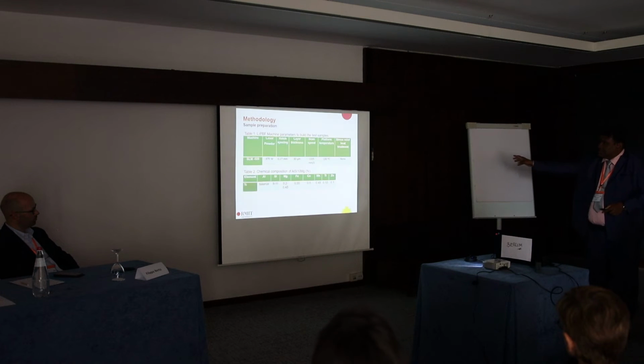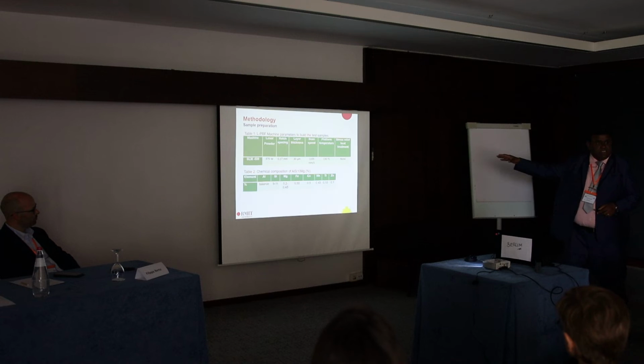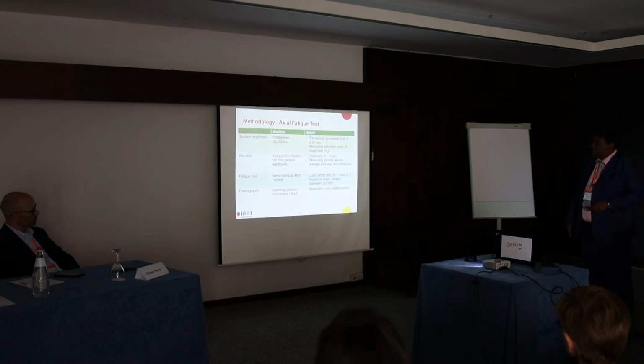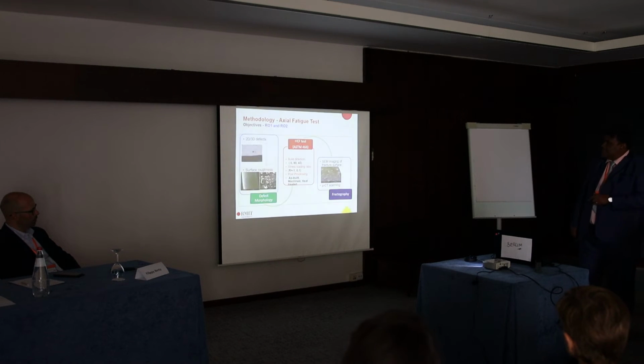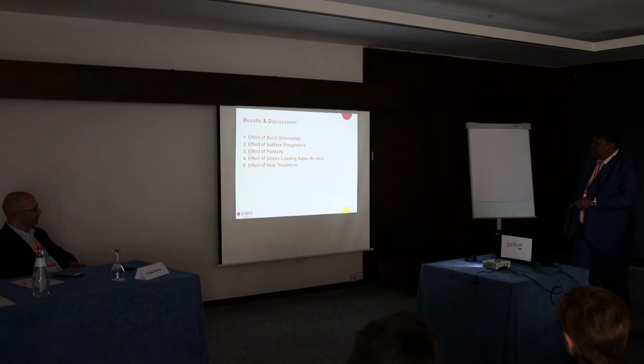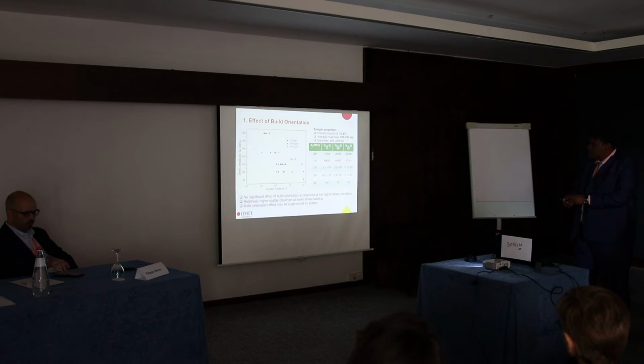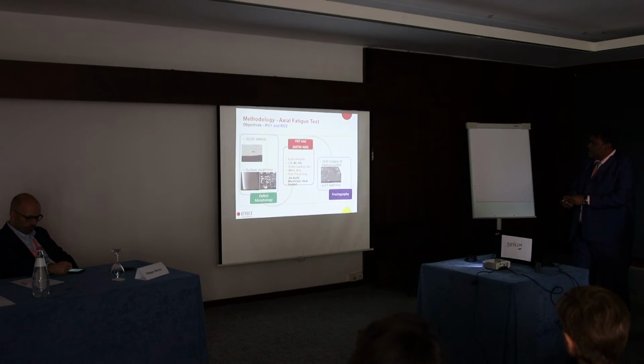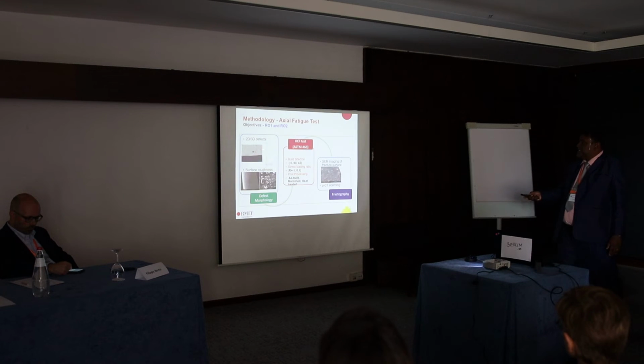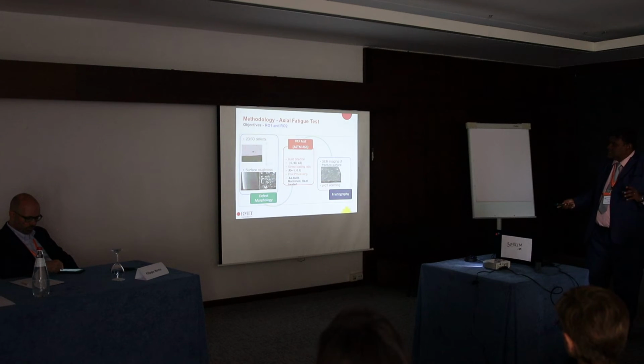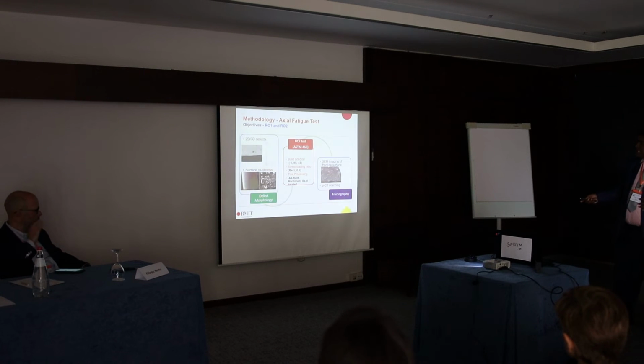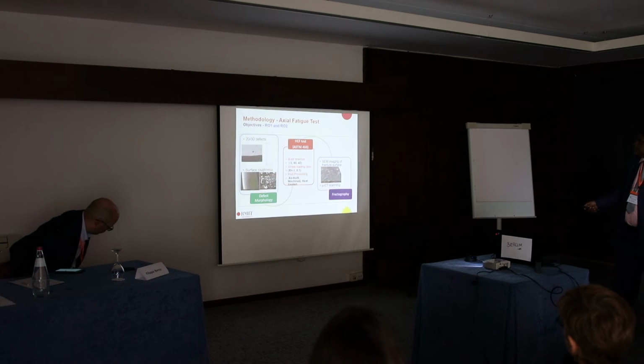This is the details of the presentation, powder composition, machining parameters. So if you're interested, I can send you the slide and you can look at it. So what we did for the axial fatigue test, we first characterized the defects in the material, particularly 2D and 3D defects and surface roughness. After defect morphology characterization, we did high cycle fatigue tests, with different build directions, different R ratios, and different post-processing: as-built and machined. We also did post-processing analysis using SEM and micro-CT scanning.